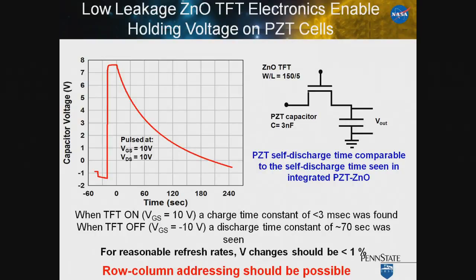We then held the voltage for some time and then turned the voltage off, and this is basically the voltage decay across the thin film, across the lead zirconate titanate, and that's associated with self-discharge across the capacitor. You can see that the time constant associated with this self-discharge is somewhere on the order of 70 to 100 seconds, so that we are able to retain the voltage for relatively long times. And what this suggests is that we have a gracious amount of time where we can hold the voltage with less than a 1% voltage ripple, so that we can go through and set by our row column addressing each of the rows in sequence.